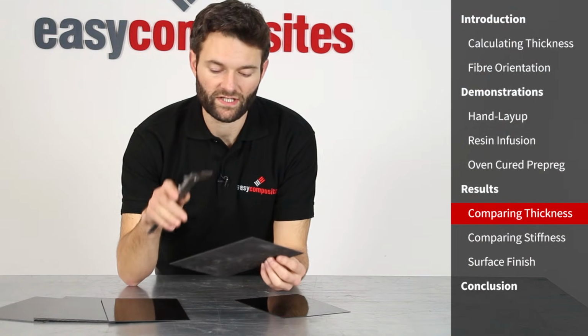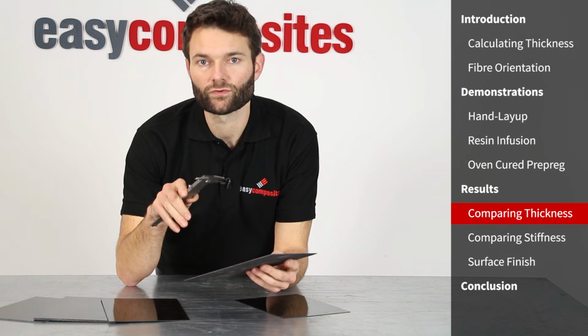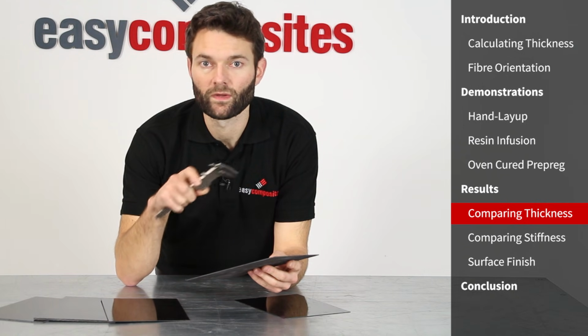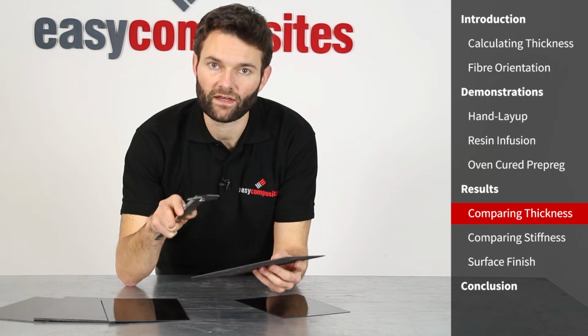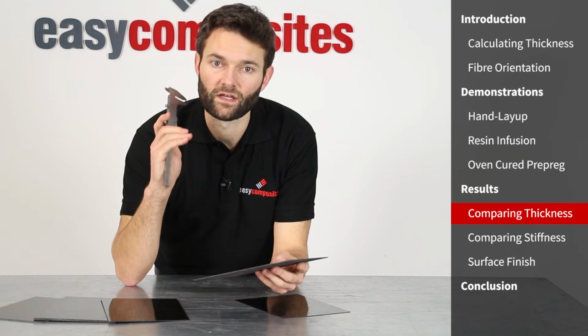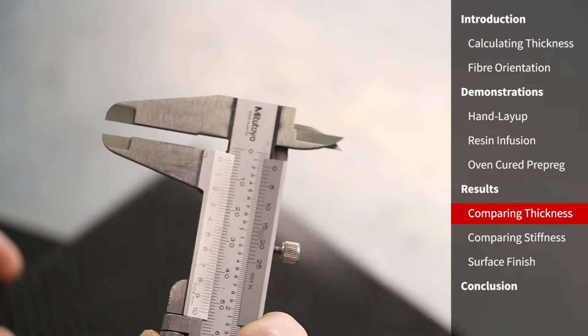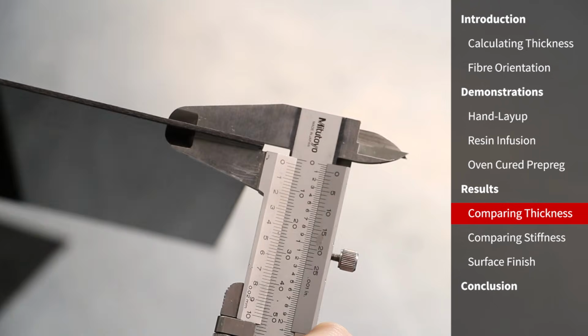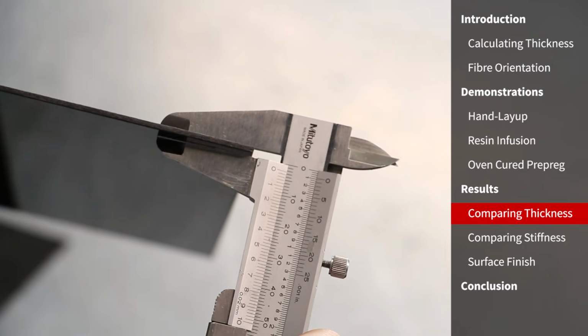We did another wet lay sheet where we had 3 layers of 200 gram and 2 layers of 300 gram, which means that we were anticipating a consolidated thickness of around about 1.2 millimeters. If we have a look on the verniers, we've got a little bit more than that. This has come up at 1.8 millimeters. And the reason, of course, for that is that this is wet lay, so it didn't have the vacuum consolidation.